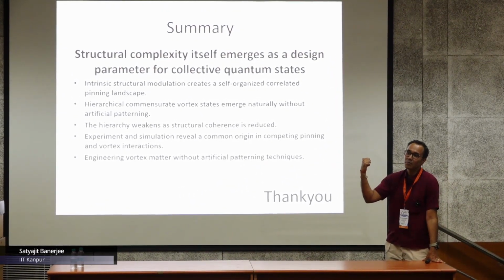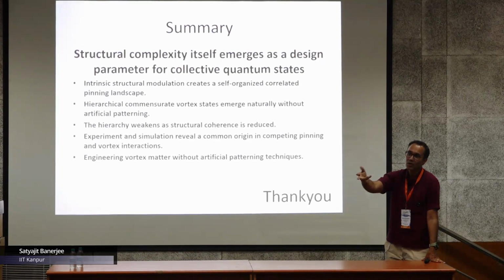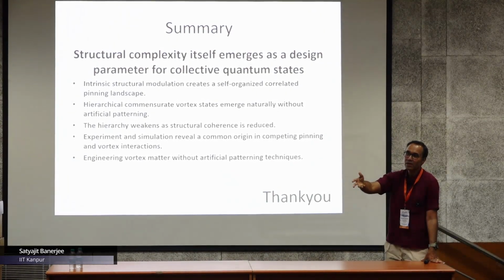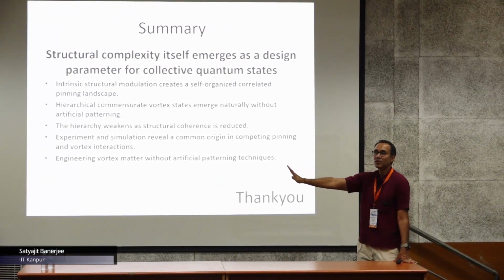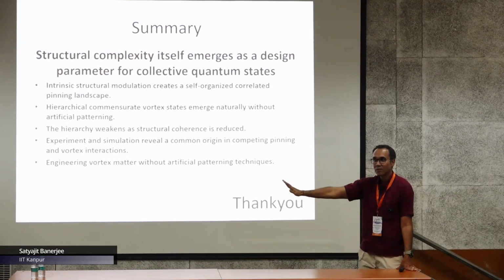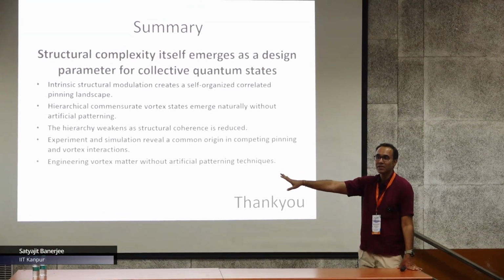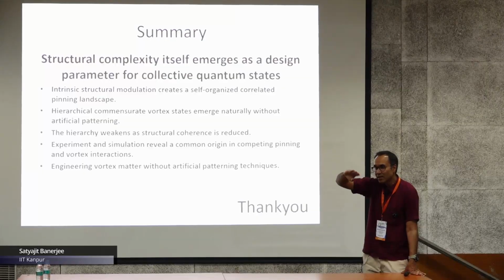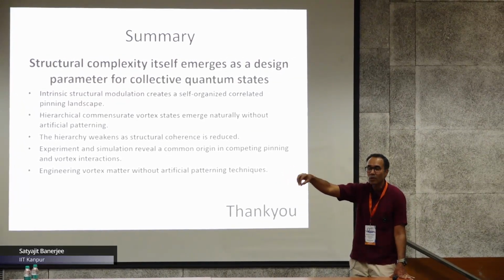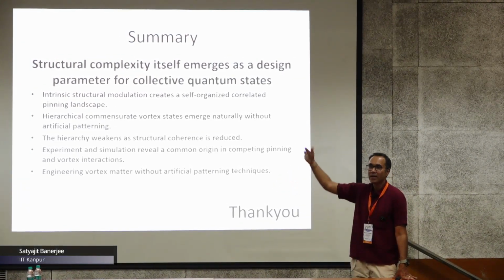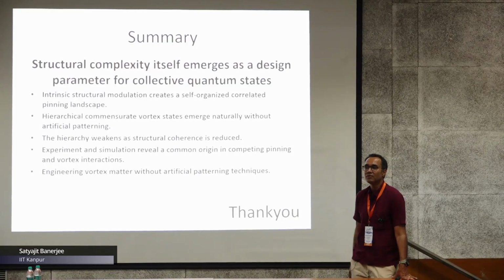That's why I showed you sample Y, that when you do annealing in a particular way, you lose the commensurability effect completely, because then it becomes a random distribution where these modulations are only present in local spots of the sample, and you can see that there are no commensurable features.